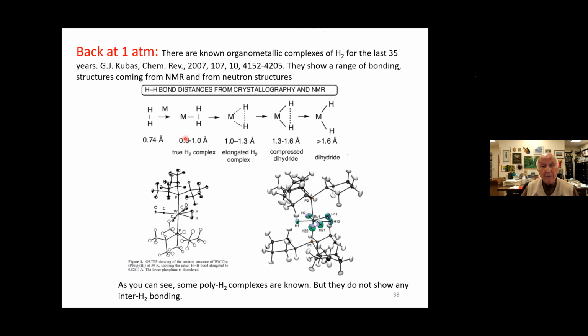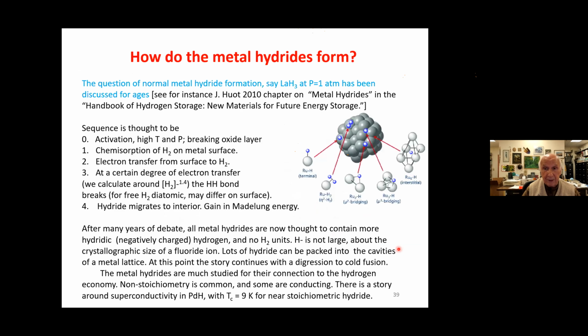And some of them are almost unperturbed, and some are stretched as long as 1.3 angstroms for the HH distance. So you have a range of these compounds. Look at these neutron diffraction pictures that you see at the bottom here. Some of them are complexes also where you have both H2 and, as you see in the one at right here, both H2 and 2 hydrides by themselves. So they're hydrogen in different forms. These are around, and it's interesting to see a connection between them and the organometallic ones.